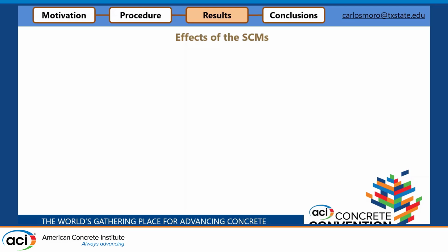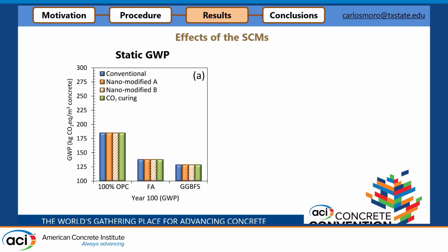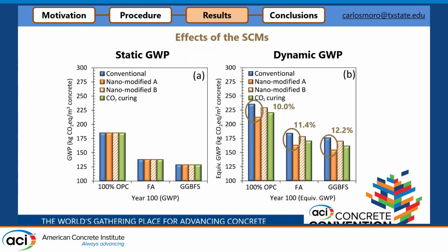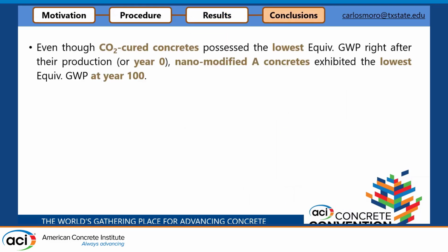All this was about OPC, 100% OPC concrete. But also SCMs could have an effect. Okay? So we did exactly the same analysis, and we see that the decreases with supplementary cementitious materials were even higher. Because the percentage decreases were higher with concrete containing fly ash and also slag. Okay? So even if we include supplementary cementitious materials in this concrete, we are producing even better impacts.